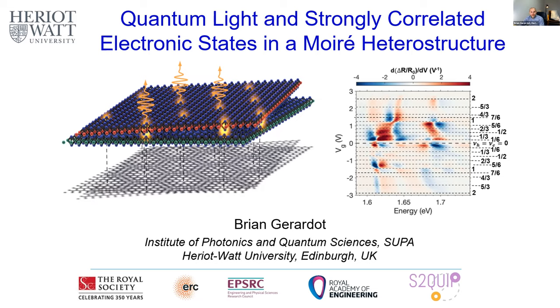So of course, the real magic of these 2D crystals is that we can combine them in any way we want and, in principle, with pristine interfaces, regardless of the lattice constant or even the relative twist between the layers. This twist, of course, leads to this long wavelength superlattice, the so-called Moiré superlattice, which can be changed by changing the angle or the different choices of materials. So this example here is for a tungsten diselenide and molybdenum diselenide heterostructure. And the Moiré period is related to the lattice mismatch and the twist angle, of course.